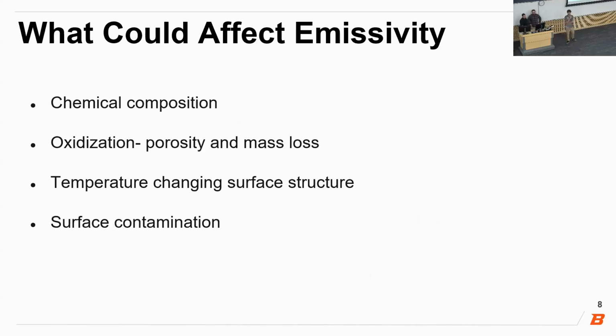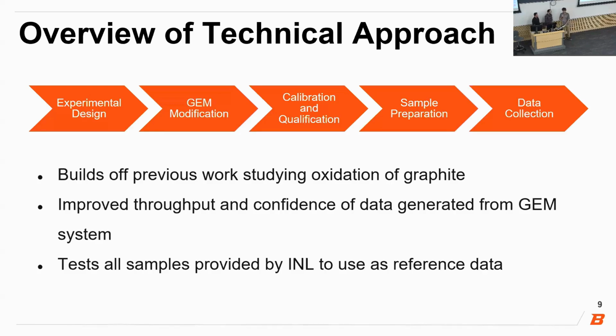So what can affect this emissivity value? The chemical composition of the surface, along with the oxidation level of the graphite causing porosity and surface changes, along with temperature and surface contamination. I'll hand it over to Dominic to explain how we did this.